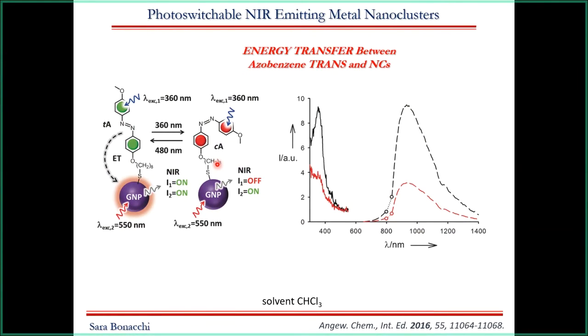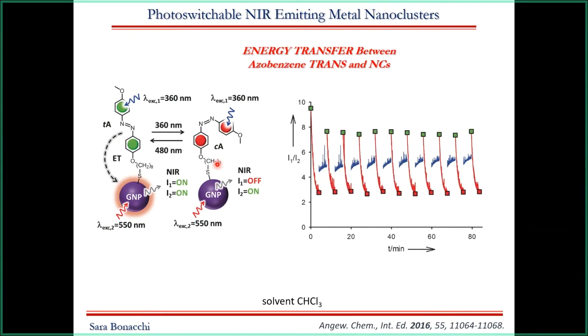And it was also possible to repeat this energy transfer process between the trans form and the gold core of the cluster several times, as you can see here in this nice plot. So it's a selective energy transfer process between the trans form linked on the metal core, which instead is not possible as soon as you switch the azobenzene to the cis form, but you can go back and repeat the cycle different times. So again, this is, I would say, the first example of energy transfer processes induced by the switchable behavior of a ligand covering the nanocluster.